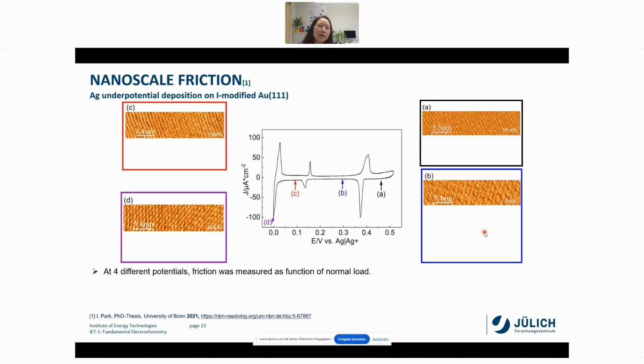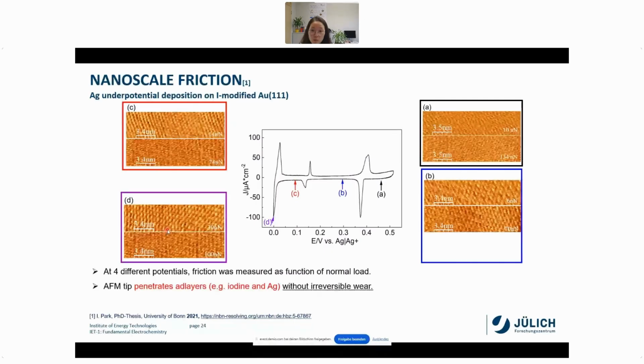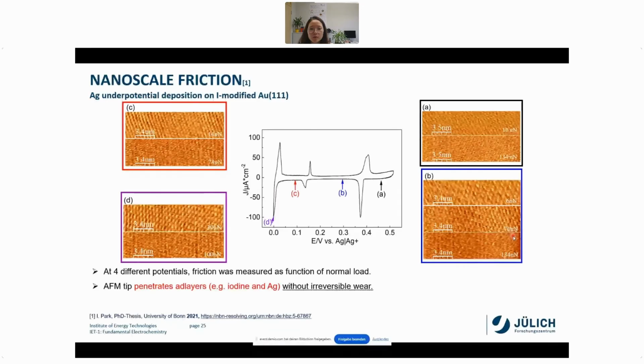Now I'm going into more detail about atomic resolution. As I said before, I used iodide modified gold 111. At a low normal load, there is always the iodide layer. When I increase the normal load, the lattice structure changes to a smaller one. And then for the blue potential, there are even more changes. So it indicates that the AFM tip can penetrate into the iodine layer or even the silver layer. Now I will show you how this penetration affects the friction.